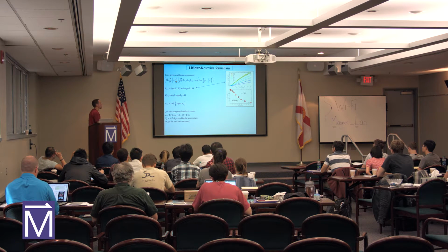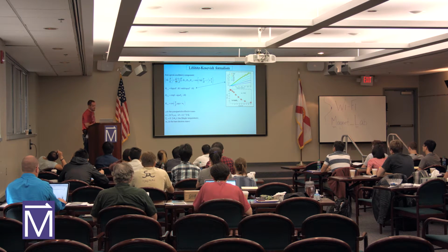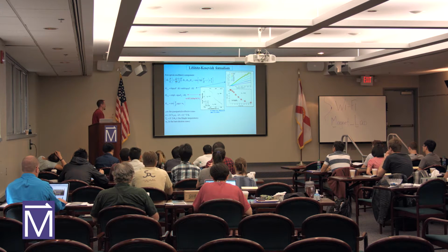You can have as much as hundreds of bare electron masses. And if this moves out to higher temperatures, you can have a very low effective mass, a very small effective mass. So if from this temperature-dependent damping term you've already extracted the effective mass, you can go on to the next term, the Dingle term.